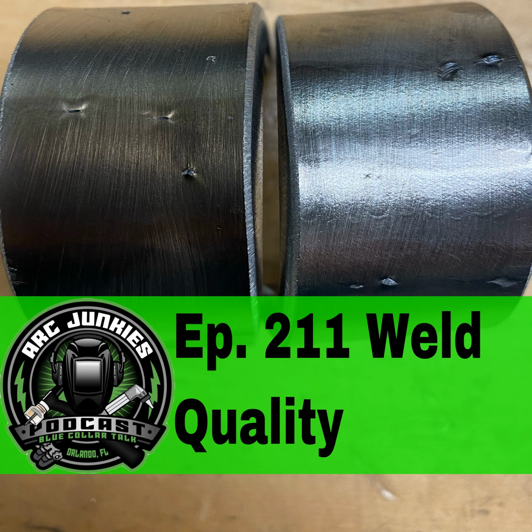When you put your electrode into your electrode holder and strike an arc, be very diligent of where you're striking your arc. A lot of times, we'll throw a rod in the stinger and we're moving around, whether it's a welding booth or out in the field, and we just bump the tip of the electrode across the material. Now we've got an arc strike. Or the most common thing I see is as we're welding along, that rod gets stuck, and we start wiggling that stinger back and forth, trying to break that arc. As soon as it breaks, it catches us off guard, and we strike it right across the material.